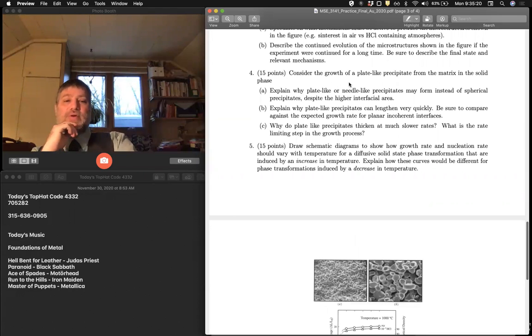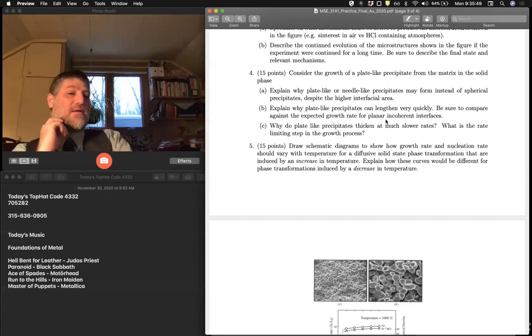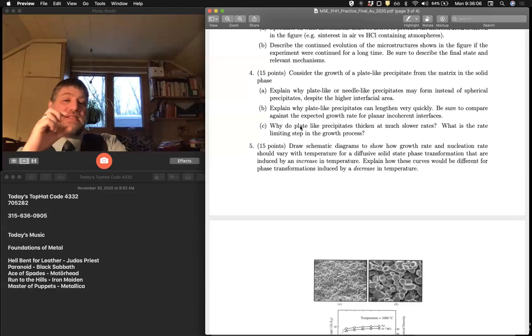The next question, I say, consider the growth of a plate-like precipitate from the matrix in the solid phase, right? I ask you to explain why plate-like or needle-like precipitates will form instead, in some cases, of spherical precipitates, even though they have a higher interfacial area. Okay. Why do plate-like precipitates lengthen very quickly? Compare the expected growth rate against the expected growth rate for planar incoherent interfaces. Right, so that's probably a clue here that I mentioned incoherent interfaces and a comparison. And then why do these plates thicken at a much slower rate? What is the rate limiting step of the growth process? Right? So again, probably a paragraph for each of these prompts, with a couple sentences. Okay.